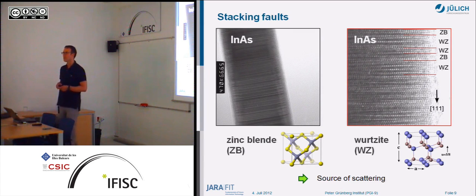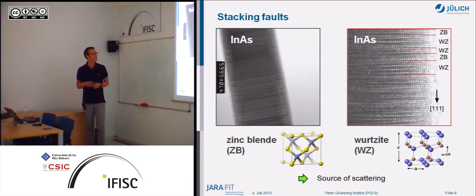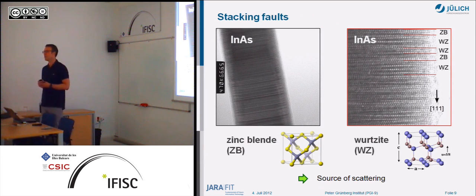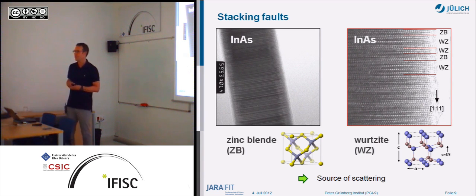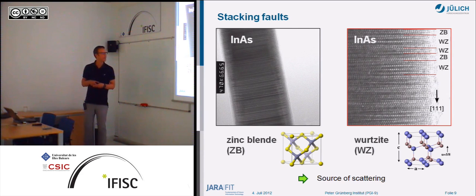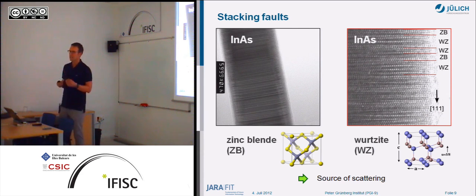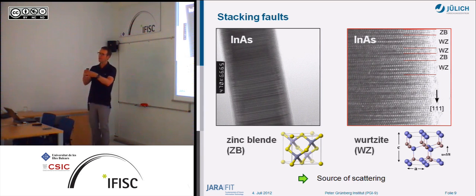If you look a little bit closer, there's an interesting issue we're studying on these nanowires. If you look from far away, you think, oh, these nanowires look perfect. But if you look closer, with transmission electron microscopy, you see that the crystal structure isn't that perfect. That's something you often have to deal with if you have nanowires. The crystal structure is kind of messed up. The reason is that in contrast to layer systems, where it's well defined which crystal structure you should grow, if you have a nanowire in just a small area, it's not that clear what is the best crystal configuration.